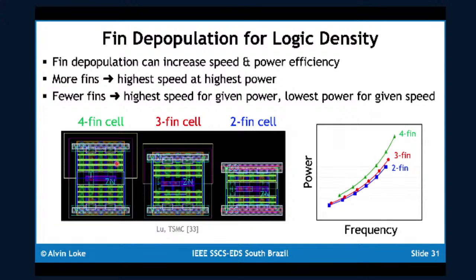As we migrate from a 4-fin cell to a 2-fin standard cell, looking at power versus frequency, you can see you're not really reducing the maximum frequency by very much going from 4-fin to 2-fin, but the power efficiency of going to a 2-fin is substantially better. So this process actually favors using fewer fins in order to get the most efficient performance for a given power.